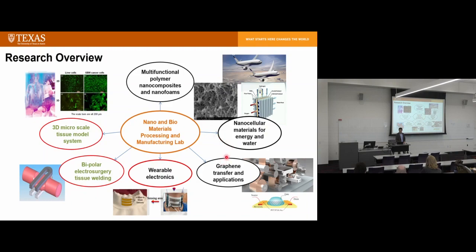And currently, another project we have been working on for a long time is graphene transfer and application. We built a large-scale roll-to-roll transfer machine, and we study the transfer process. We take graphene off of the growth substrate, which is copper. We grow monolayer graphene, and then we delaminate it and transfer it onto a polymer substrate and use it for further applications. We're also looking for applications using graphene.